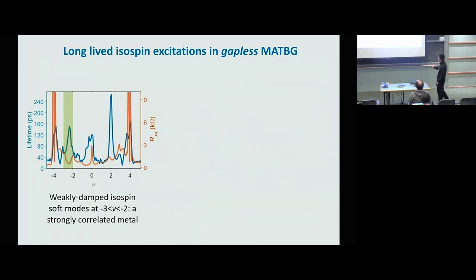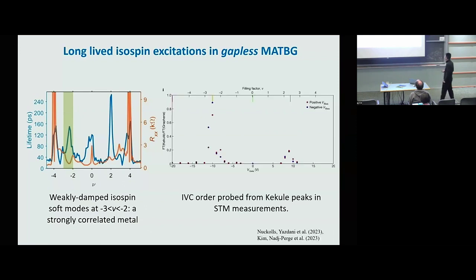And this is actually a very interesting filling range because there are several other interesting observations happening at this filling range. In particular, in both MATBG and MATTG, IVC order have been probed from STM measurements. And so here is a plot from these 2 papers, which shows us the strength of the IVC order as a function of filling. So the top is the filling.